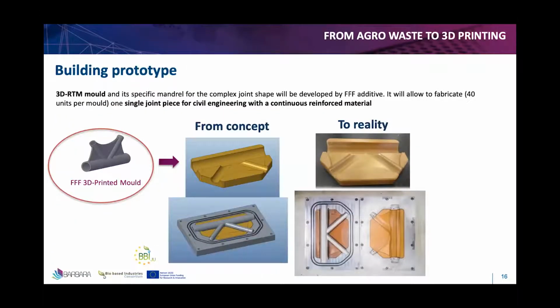For the construction sector, we built the 3D RTM mold mentioned before. In the pictures, you can see the concept, the original design, and the 3D printed mold with its aluminum case. To build the monolithic mold concept was a challenge in itself for the 3D printing technology. In this case, trying to solve the differences in the thermal expansion coefficient between the aluminum and the polymeric material was technically tricky. The result was quite successful, and about 40 joints were obtained. An epoxy resin with glass fiber was used for this purpose.